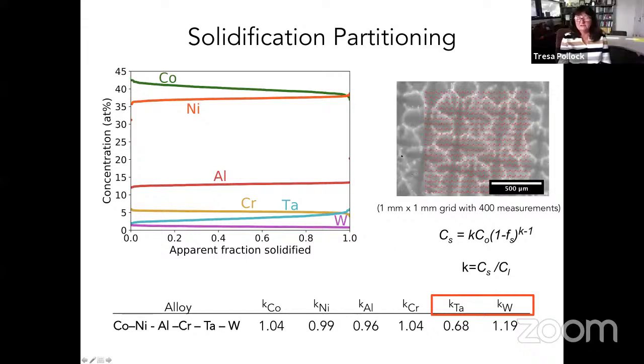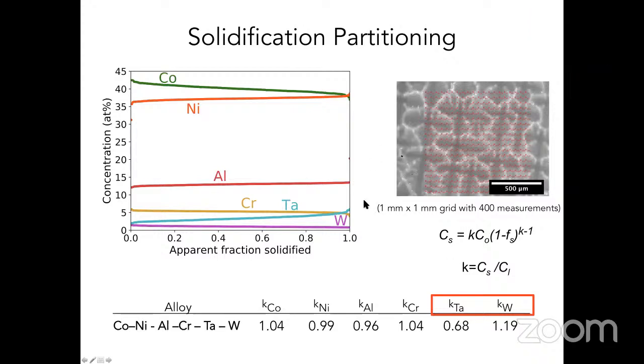So it's basically what we do is fit the Scheil equation to these curves. So if you measure the composition at the core of the dendrite, that's the very first solid to freeze. If you measure the composition in the interdendritic region, that's the last solid to freeze. And so we're just basically taking all of this data, ranking it high to low, and then fitting the Scheil equation to it. Gotcha.